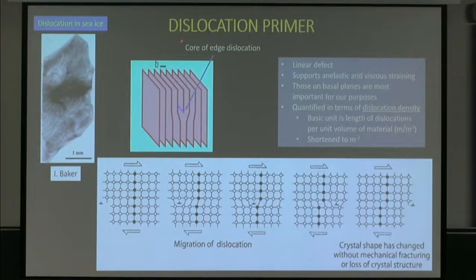A little cartoon here showing the nature of these. So if you have an atomic structure that has a discontinuous and interrupted atomic plane, kind of like a sheet of paper partway through a stack, that spot there is a dislocation core. It's a jog in the crystal structure. If this is our crystal structure at various points during straining, our dislocation can actually break bonds and reform bonds along this plane such that from the beginning, over here on your left, it passes through the crystal, pops out on the other side. The net result is 1 Burgers vector of straining for this piece of ice. So we have that as our mechanism, and that's been quantified.